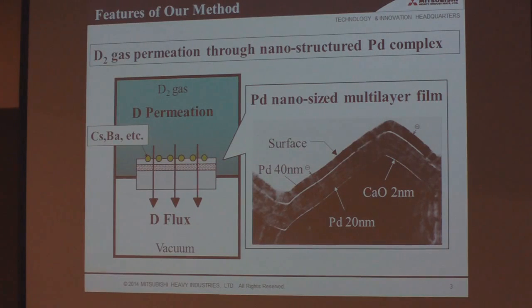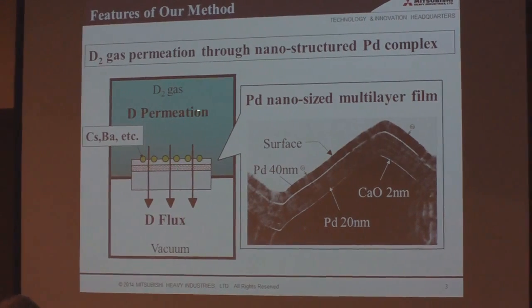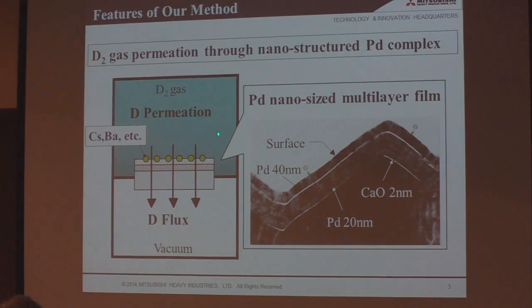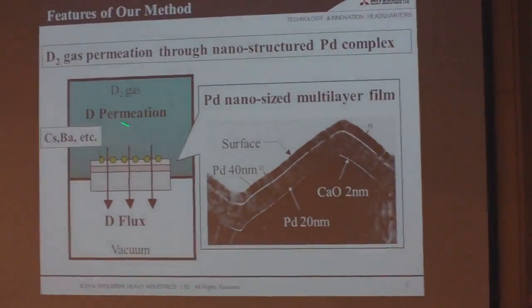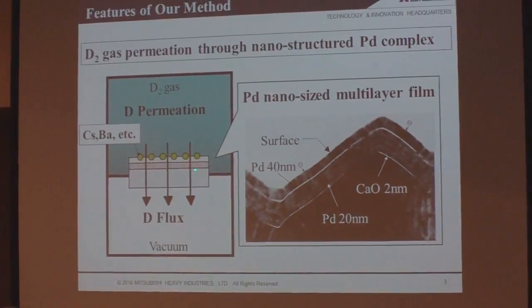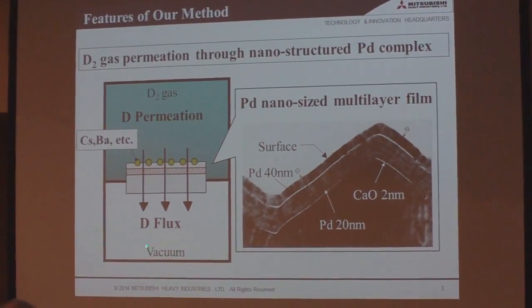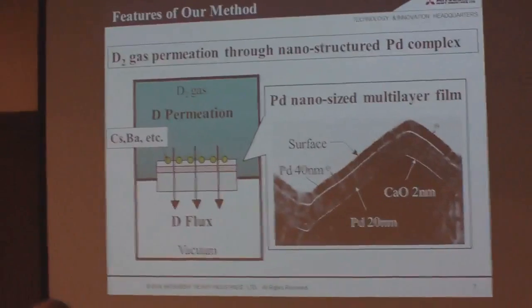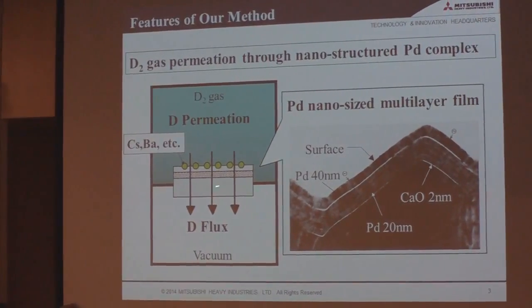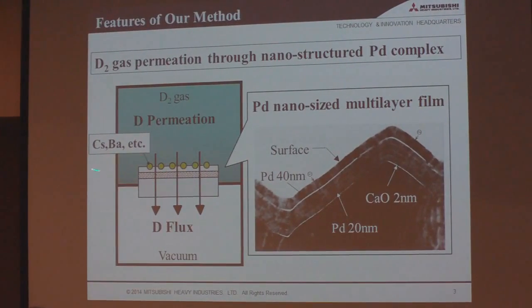And then we put this multilayer thin film here, and we fill this region with D2 gas. On the other side, we keep vacuum condition, and D2 gas dissolves on this surface and permeates through like this. And then we can observe the transmutation reaction on the surface. That's our method.